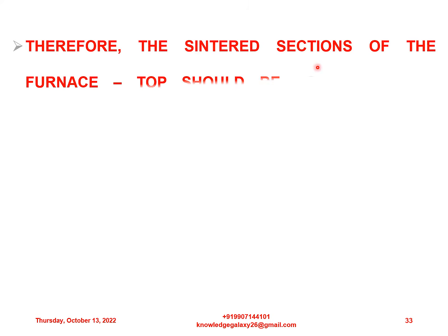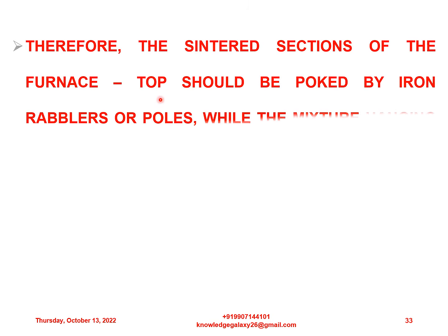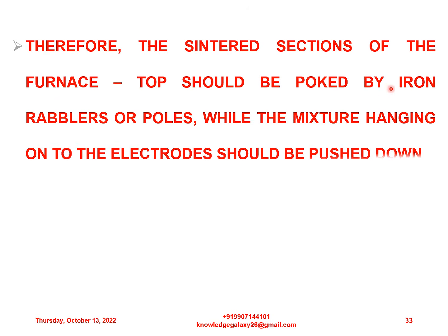Therefore, the sintered sections of the furnace top should be poked by iron rabblers or poles, while the mixture hanging onto the electrodes should be pushed down.